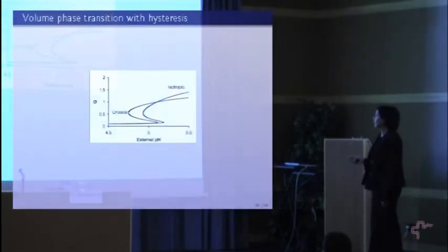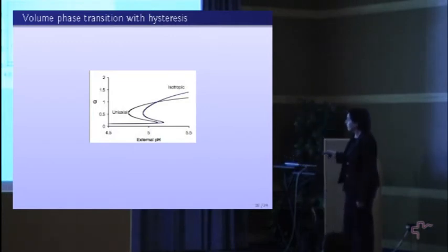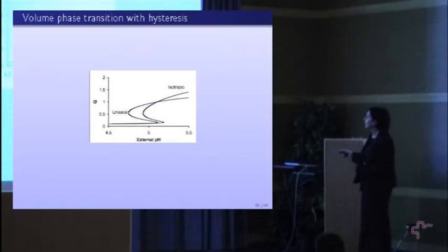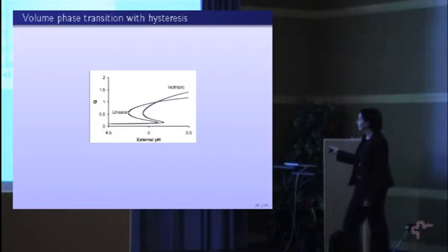Okay, so now here there is another situation where we have hysteresis. So these are under two different mechanical conditions. So we see that for a while, here there is a concentration. This goes with the pH of the device. And so, for example, if we follow one of these, we go up to here, and then the system jumps to the top branch. However, when we come down, the system goes down to this end, and it jumps at a lower pH.